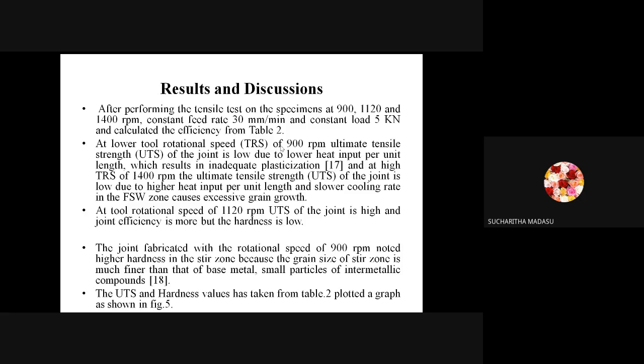At lower tool rotational speed, TRS meaning tool rotational speed, of 900 RPM, the ultimate tensile strength of the joint is low due to lower heat input per unit length. Actually, the friction developing between the tool and workpiece increases with rotational speed, and the temperature distribution on the surface of the plate increases. At lower speeds, the tensile strength is low. At more speeds, more than 1400, again the tensile strength decreases. Why? Because proper heat distribution should be there on the surface of the workpiece. So at a tool rotational speed of 1120 RPM, the ultimate tensile strength of the joint is high and joint efficiency is also more.